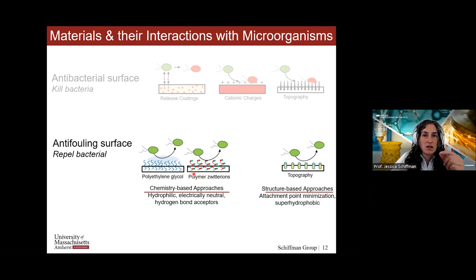So in the case of the polymer zwitterions, instead of having this hydration cloud made by this hydrogen bonding, we actually have a very tight cloud of these charge groups. And it's that close proximity of those opposite charges that really makes that same sort of hydration layer on the surface of a material. And here's a little bit more about the mechanisms by which these two kinds of coatings work.